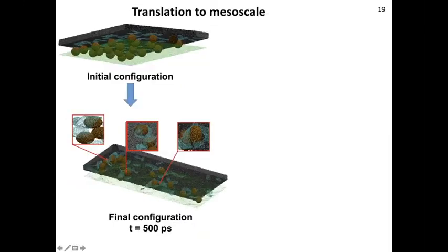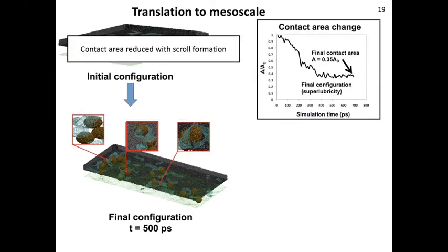Once we did this, we observed it happening for just a single flake, but what will actually happen, because we are again in the macroscale regime, where we have many of these graphene and diamond particles distributed on the surfaces? So we ran a mesoscale simulation, and we observed that many graphene flakes combine with diamond nanoparticles in such a way, creating these diamond bearings. The interesting thing is that not all of them combine. You can still see some graphene patches here, and some uncoated diamond nanoparticles, but around 65% of our existing diamond plus graphene systems are combining together to produce these ball bearing systems.